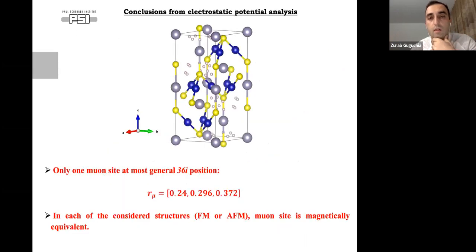hypothesis, we first calculated the muon stopping site, because we had to know where the muon sits. After quite some work, we find that there is only one muon site, at this Wyckoff position, and so this is a very stable site. Once muons are trapped, they really stop in this position and do not move at high temperature. We also find that in each of the considered structures, ferromagnet or antiferromagnet, the muon site is magnetically equivalent, which means that in both magnetic structures we expect only one magnetic peak, or one frequency.